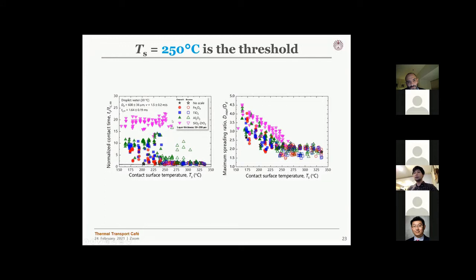And now the data plot shifted toward the left, the lower temperature region. And now you see the clear trend, clear transition between the two different regimes, both in the contact time and the spreading ratio.